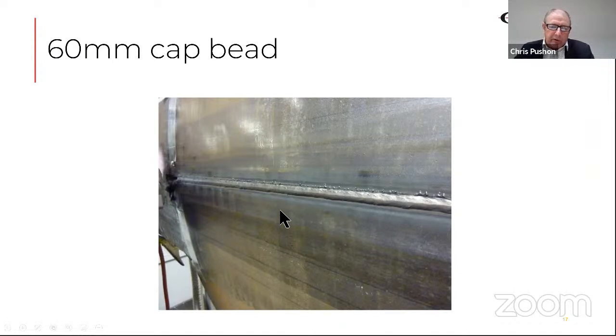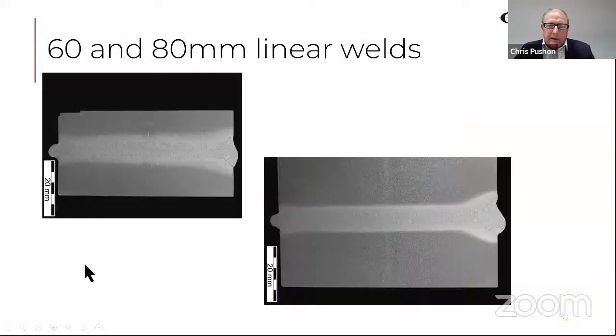What you also notice is there's very little in the way of cleaning. This has still got the oxide scale from the rolling process on, so we don't do a lot of cleaning. And that's by virtue of the fact that the pressure we're working at is several times higher than traditional electron beam welding. So several orders of magnitude higher. Another benefit is that if you increase the thickness of your component to 80 millimeters from 60, the welding process time is exactly the same. You just use more power and weld at the same speed.